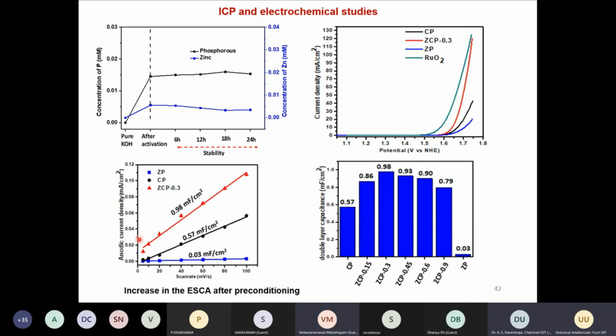So this is again the anodic current density, and we have calculated the Faraday efficiency and the electrochemically active surface area. Again, what we found is the double layer capacitance is very low for only zinc phosphate. Cobalt phosphate is higher to some extent, but particularly zinc cobalt phosphate with 0.3, that is 30% of zinc, you see a higher activity. For all the zinc-doped samples, there's only a slight difference in the double layer capacitance. And you can also see that the activity is also very similar. I have not shown it here, but its activity is also very similar.